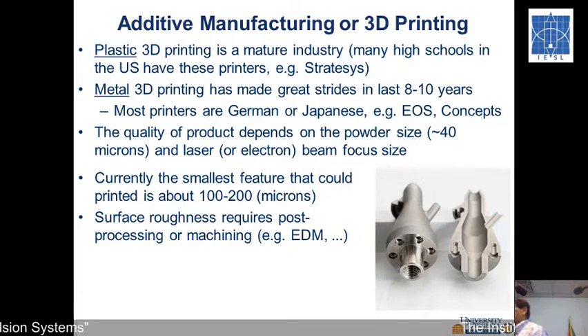If you have a cooling channel inside a big block, and you start from the bottom, you have the cooling channel. The bottom part is very easy to print layer by layer. When you come to the top, you essentially have a ceiling, a hood, and typically the particles can melt and fall down and form stalactites. And if those form, then after you finish printing, you can't get the powder out.